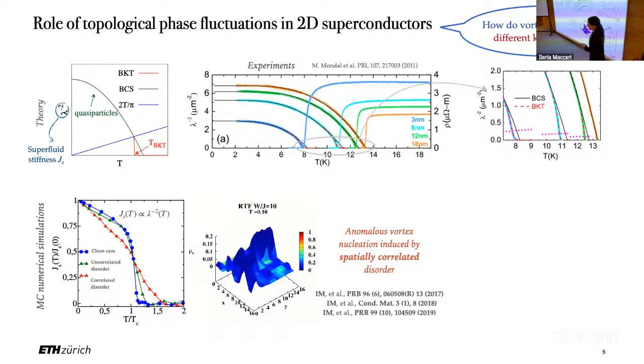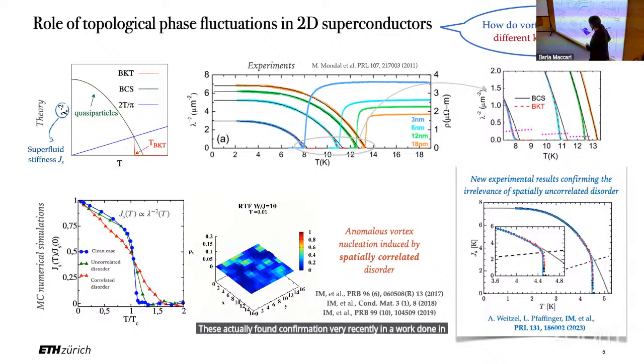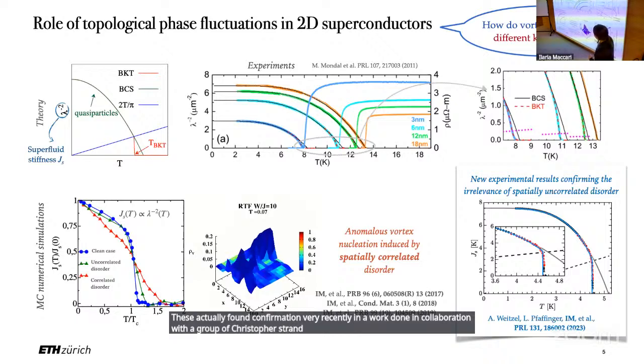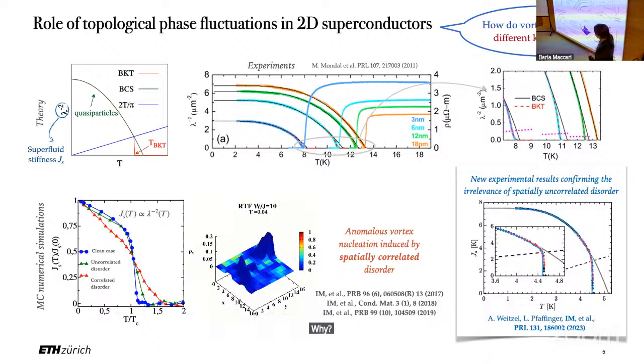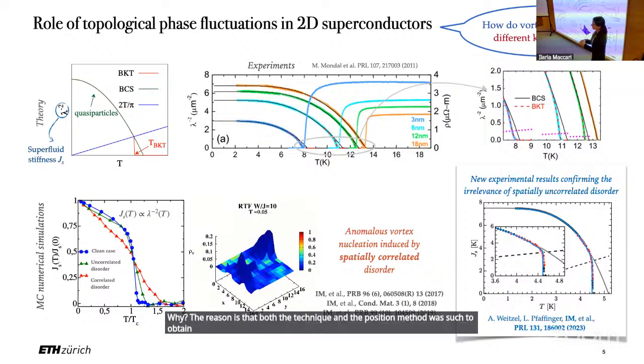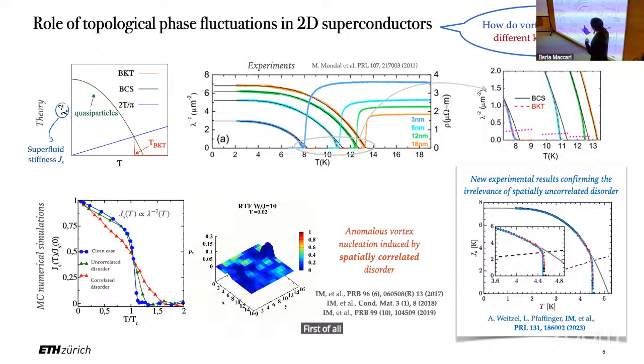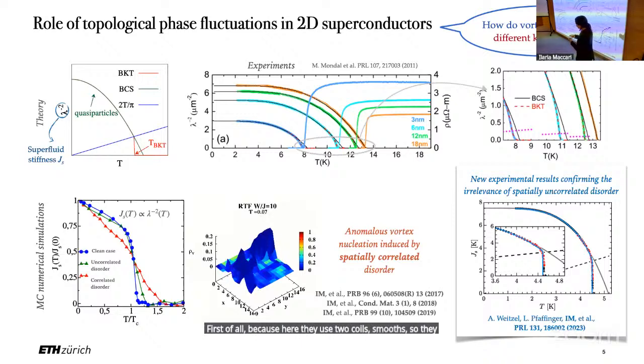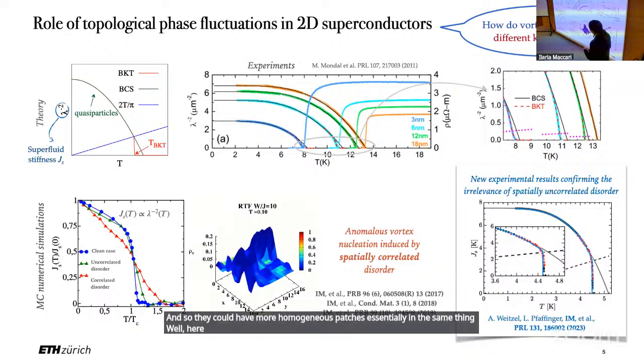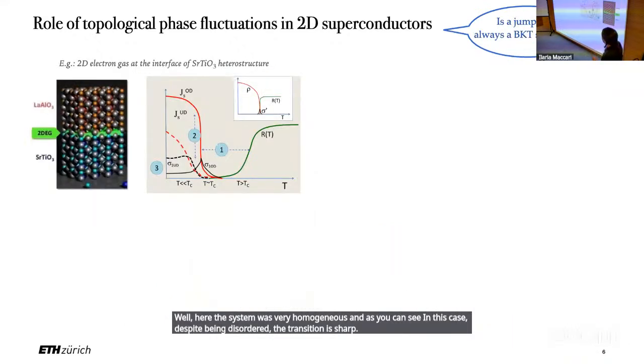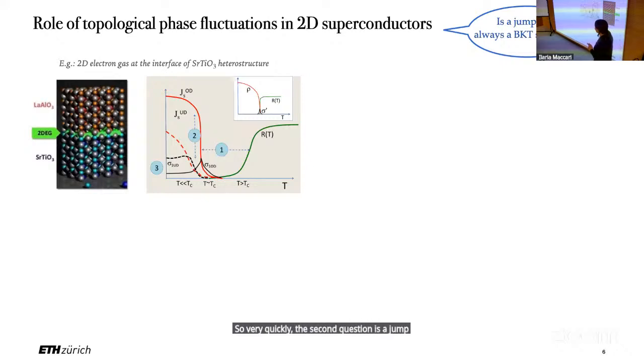This actually found confirmation very recently in a work done in collaboration with the group of Christoph Strunk, where they observed a very sharp jump for the superfluid stiffness in the same materials as this measurement here. Why? The reason is that both the technique and the deposition method were such as to obtain a sample that was more homogeneous. First of all, because here they use two coils, mutual inductance, so they require larger samples, and so they could have more inhomogeneous patches, essentially. While here the system was very homogeneous, and as you can see, in this case, despite being disordered, the transition is sharp.